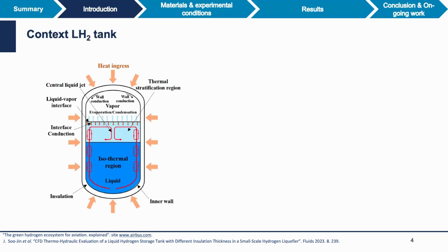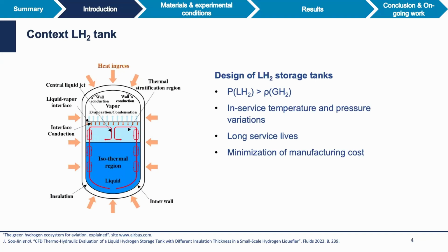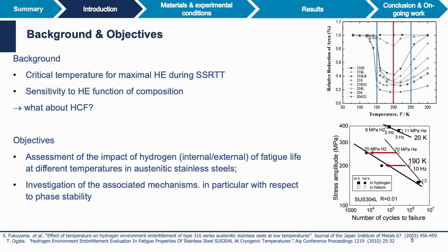And you have also to imagine some type of worst case scenario where, for some reasons, the tank could be placed at quite elevated temperature while exposed to hydrogen, and you could have a significant hydrogen uptake. Okay. So for this type of application, austenitic stainless steels can be good candidates as a replacement for aluminum alloys, as we have seen this morning. And the question is about the hydrogen embrittlement of these materials at low temperature.